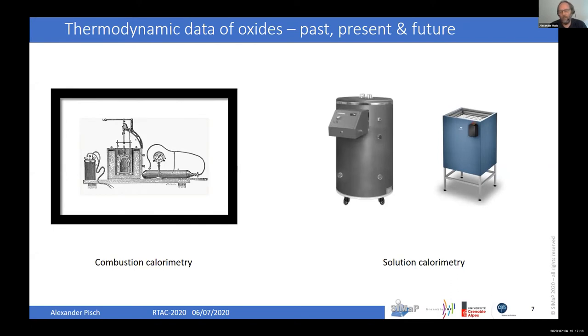On the right side, solution calorimetry is then used if you have higher order oxides, because then you can refer them to the simple oxides that you measured before by combustion calorimetry. Basically you have two methods: either solution calorimetry at moderate temperature using borates or molybdates as a solvent, or you can use aqueous chemistry using acids as a solvent. With this equipment, normally you should get a nice value for the heat of formation, but still you would need the data for the temperature dependence.